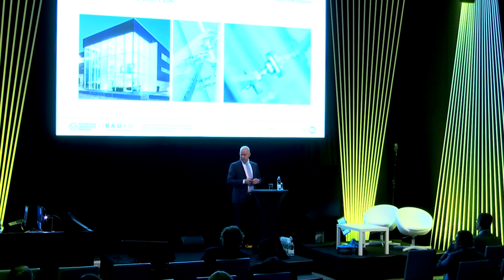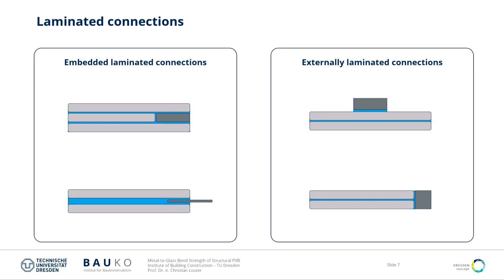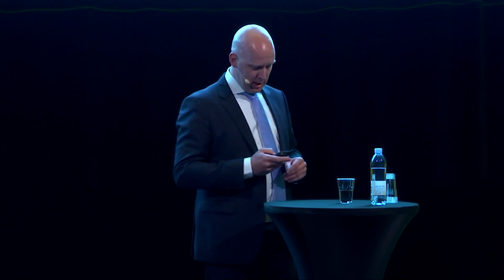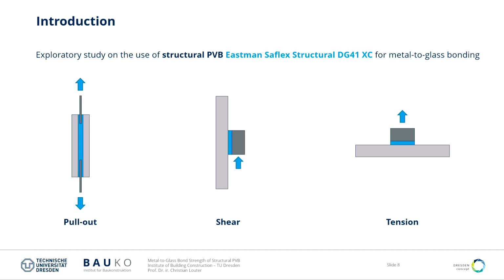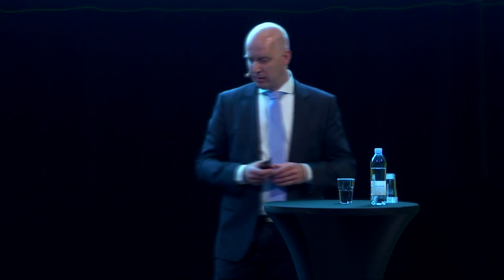So just to set the scope a little bit of the presentation, what I would like to look at today is these two options, so that we embed something with a thin metal into the glass and that we externally laminate something on the outside of the glass. And we do that with, let's say, a newly appearing product on the market, a structural PVB from Eastman, Saflex DG 41, which is a stiffer PVB than the regular PVBs. So we just did this exploratory study on what are the potentials of this structural PVB to laminate, to glue metal to glass.